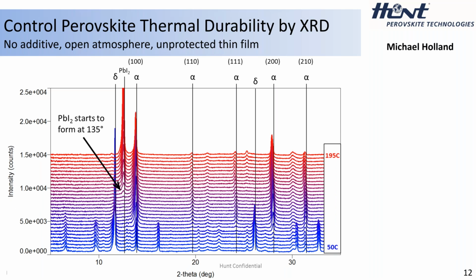This was something that was really common in the literature back in the early days. I think Joe actually showed me these data first, before they were published, that in the annealing process you actually had an intersection between annealing and degradation, where the material would start to degrade before it fully annealed. And that's certainly an issue, right? If you can't fully anneal it, form the perovskite in situ by which the process progresses, then you'll never make as good a perovskite as you can. So you've got to be able to isolate these two things. Having this high threshold of 195 C allows a large window of processing temperatures.